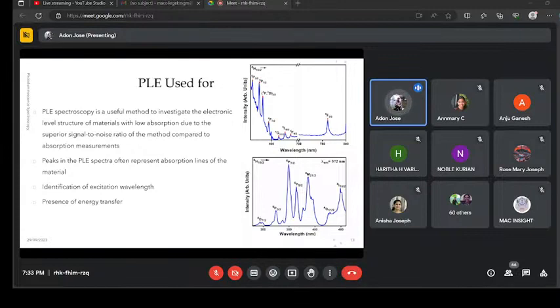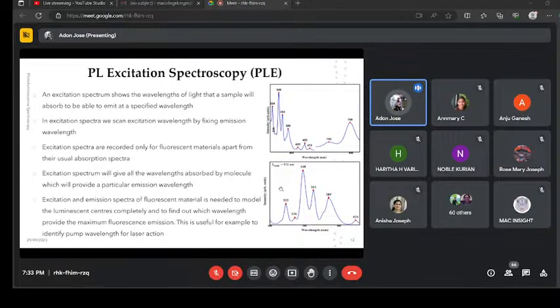If we are observing this slide, we can say that the intense excitation band lies at 348 nanometer. So if you record the emission spectrum by exciting at this particular wavelength, we can observe the maximum luminescence from that particular material. The spectra gives the idea that all these 6 excitation wavelengths can give the luminescence spectrum from the material, but the intense luminescence is observed only when we are pumping the material with this intense excitation band.